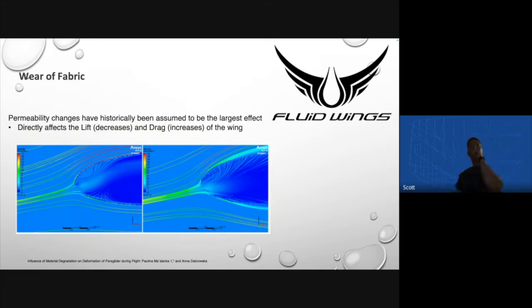So can you imagine if the flow starts to separate in that critical section, what happens? Typically, you lose lift and you increase drag. What does that translate to you as the pilot? A wing with higher porosity starts to lose lift, and increase drag. So what's going to happen to your descent rate? It's going to increase, right? Because lift goes down and drag goes up, and your glide ratio is L over D. So all of a sudden you start coming down faster.